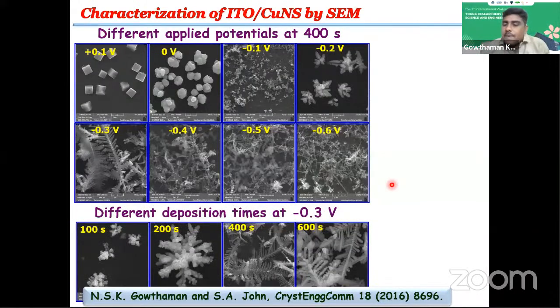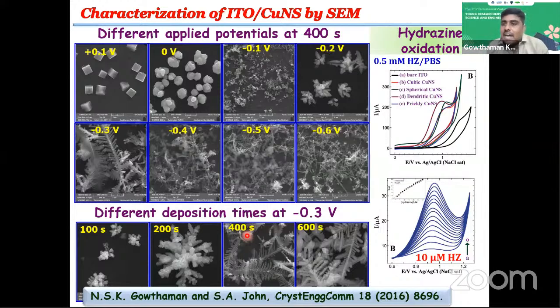At different deposition times, we are focusing on the dendritic nanostructures because of their open porous structure, high porosity and high surface area. We focused on the dendritic nanostructure at different deposition times. At 400 seconds, there are well-formed dendritic nanostructures, and we utilize these nanostructures for hydrazine oxidation.